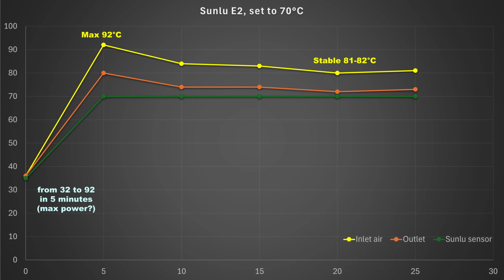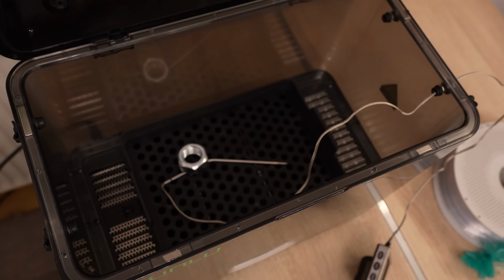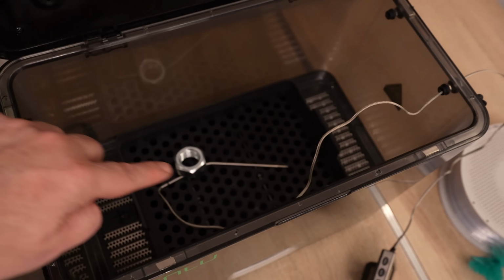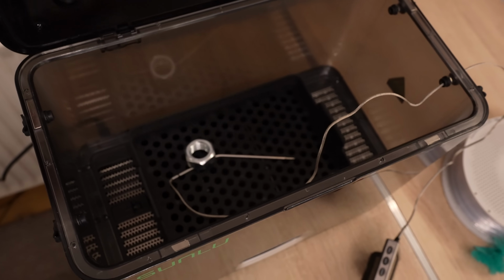And again, in the first 5 minutes, until it reached those 70 degrees Celsius according to its own sensor, it operated at maximal power. The air reached the temperature of 92 degrees Celsius, and only later it stabilized around 81 or 82 degrees. For the annealing, I inserted the tray, and the sensor will be exactly in the center.